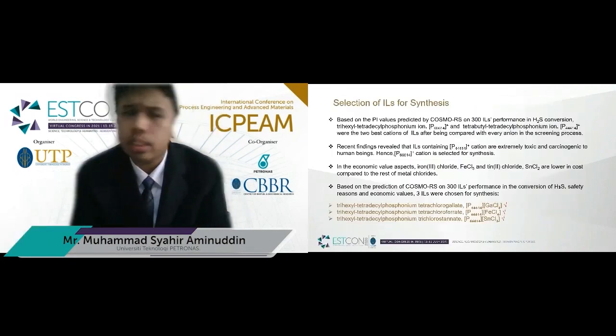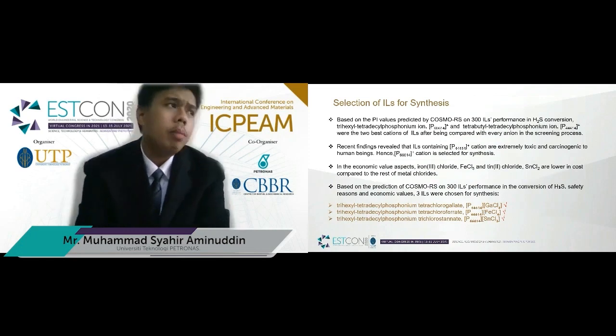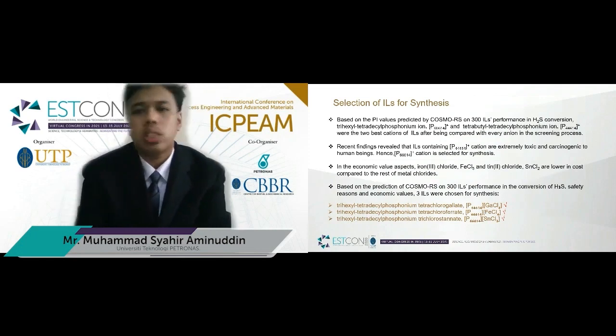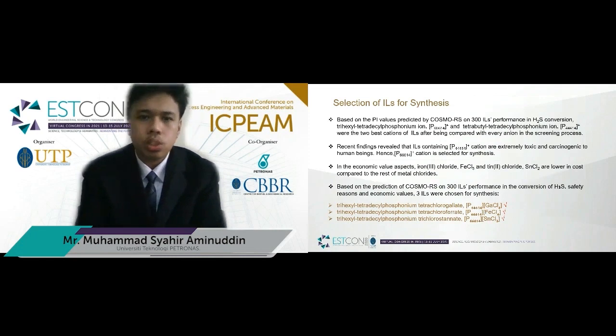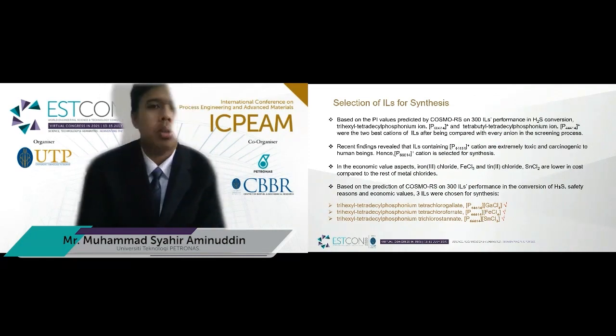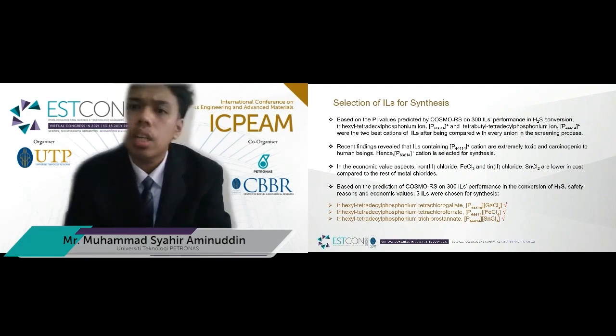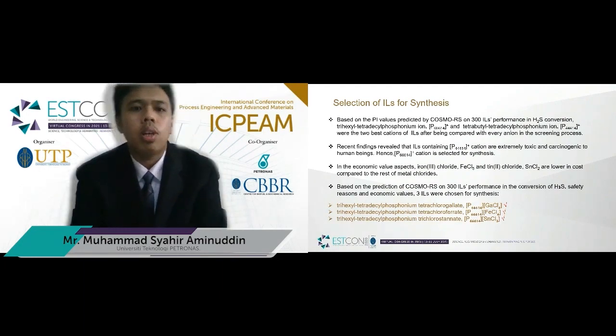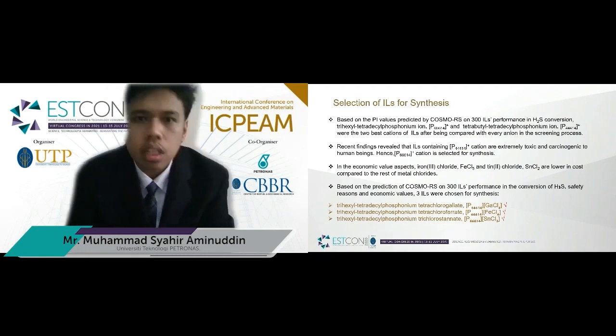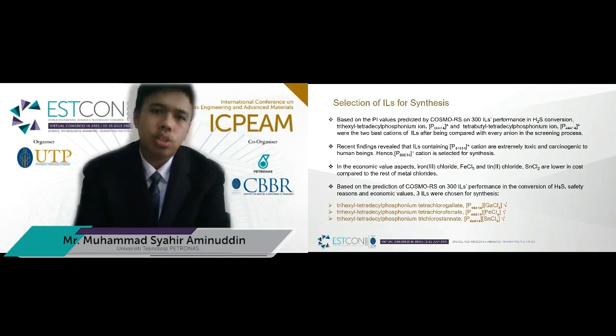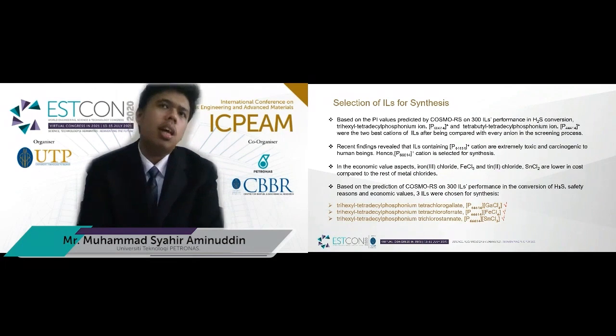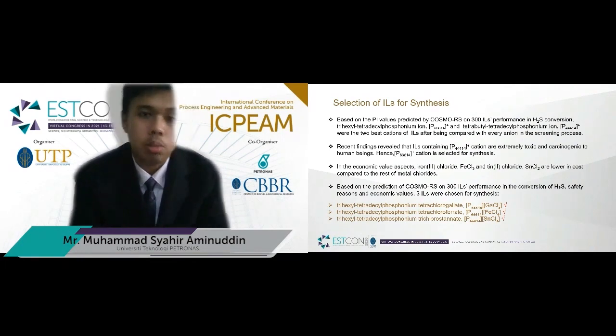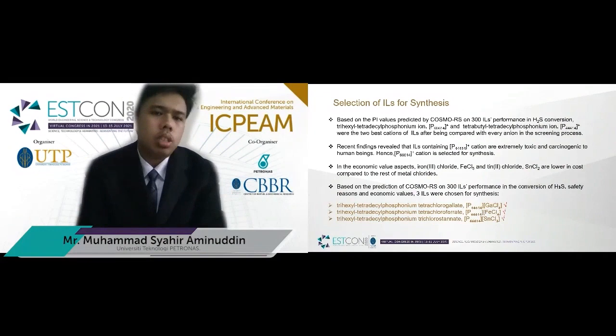Then we will proceed to the selection of ILs for synthesis. Based on the PI values predicted by COSMO-RS on 300 ILs performance in H2S conversion, trihexyl tetradecyl phosphonium ion P66614 and tributyl tetradecyl phosphonium ion P4414 were the two best cations of ILs after being compared with every anion in the screening process. Recent findings reveal that ILs containing P4414 cation are extremely toxic and carcinogenic to human beings. As a result, this production has been stopped. Therefore, P66614 cation is selected for synthesis for safety reasons.